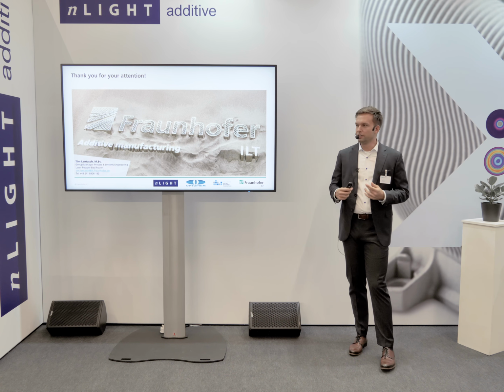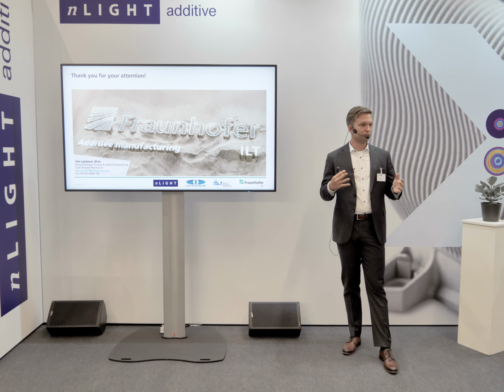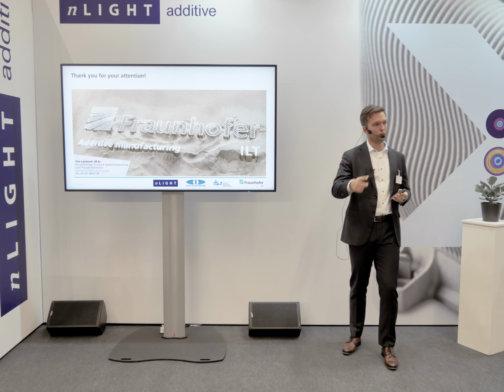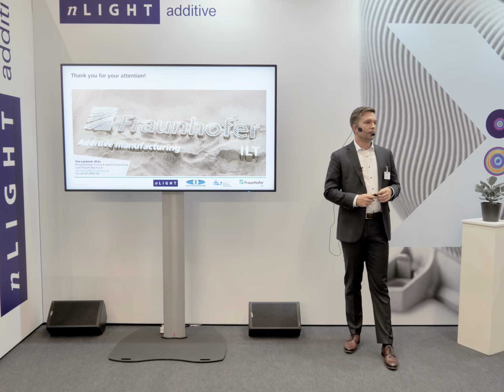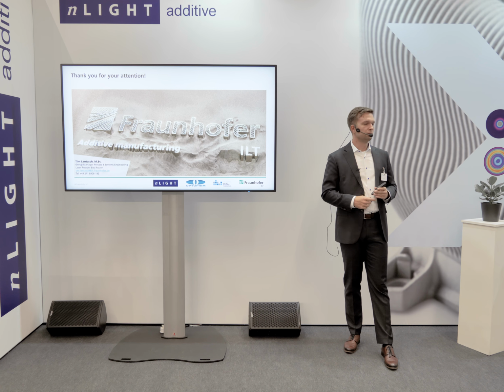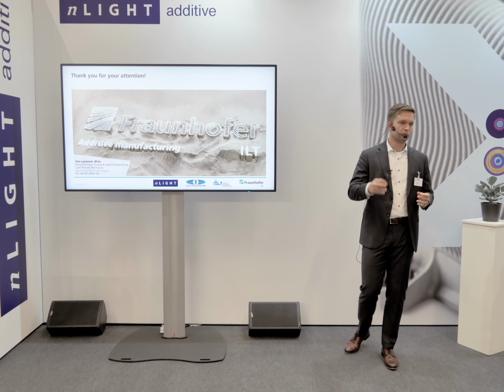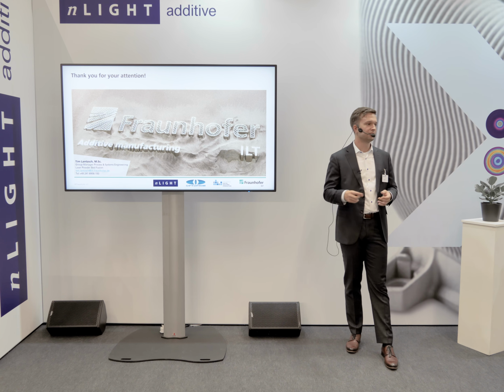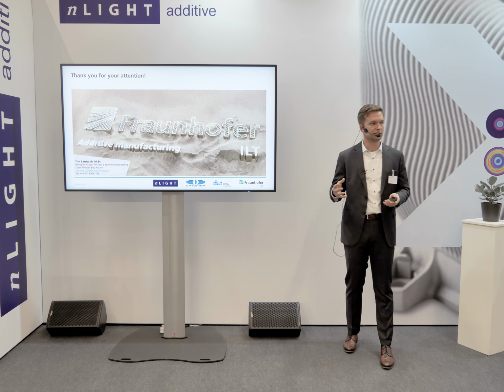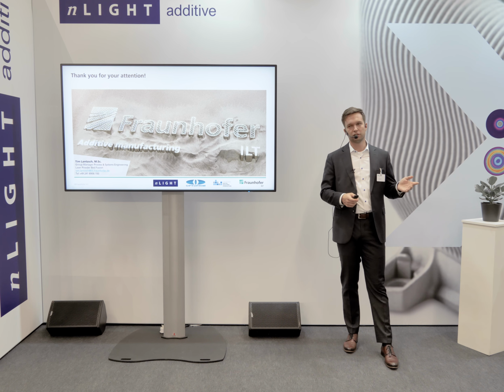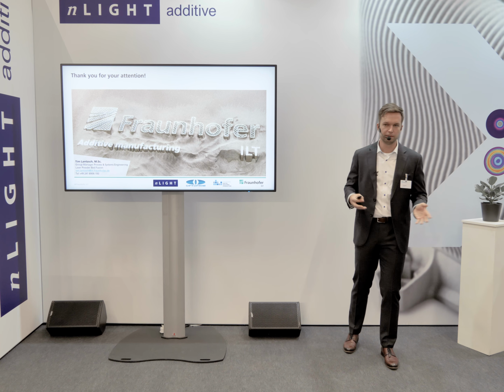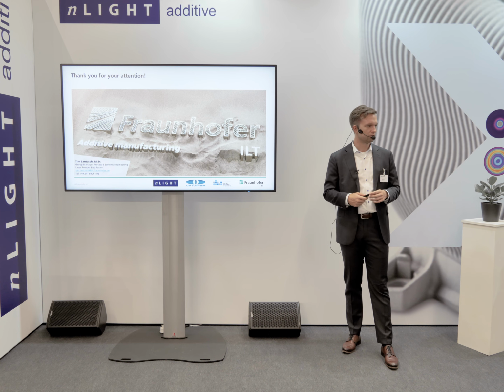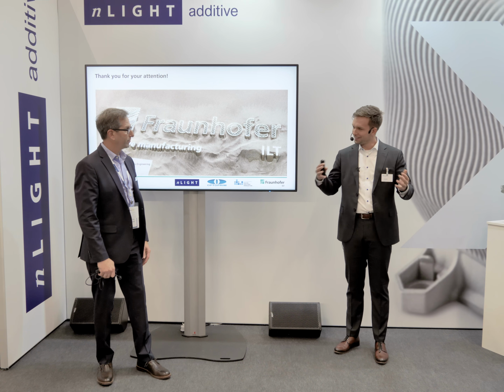Yeah, that's actually also a very interesting research topic for us, not only for different beam shapes, but also just in general, the processing with temporal modulation, meaning pulsing, but you could also think about wobbling or something like that. I think it could be beneficial if you want to really fine-tune, for example, microstructure. If you combine then what you know from pulse modulated processing, that you have some kind of discrete solidification with smaller independent melt pools, together with the fact that the melt pool that results will probably be rather shallow and wide, this could also be an additional degree of freedom you could use to fine-tune your part microstructure, for example. Yeah, thank you for inviting me, and it was a pleasure.